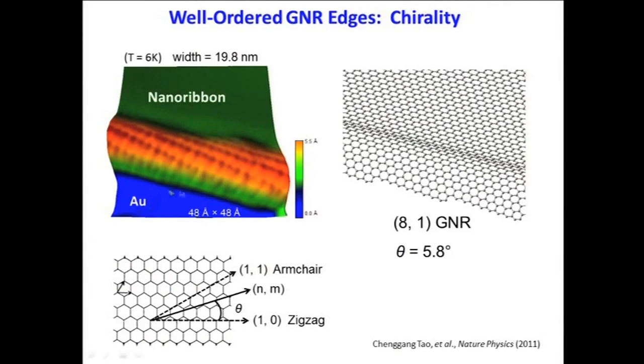So first I want you to see that we have a nice, straight, well-ordered edge, and because we can get atomic resolution for this region near the edge, that allows us to determine the chirality of the edge. So now we can actually directly determine the chirality of the edge by simply looking at this angle with respect to that angle. And that allows us to determine that this nanoribbon, for example, has an 8-1 edge, which means that it goes zig, zig, zig, zig, zig, zig, zig, zig, 8 times and then zag.